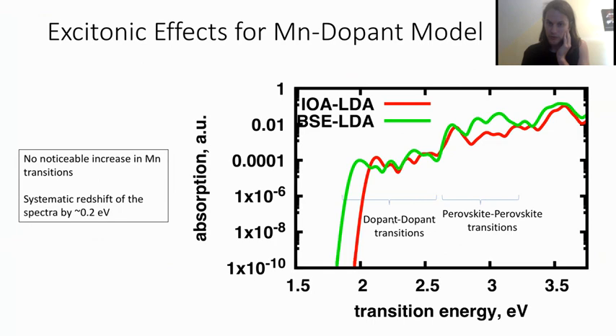So the red line is independent orbital, and the green line is Bethe-Salpeter. The main takeaway is that there's a consistent small redshift of about 0.2 eV. That can be represented as a binding energy of sorts. One thing we were hoping for, or a hypothesis, is that including excitonic effects would boost the oscillator strengths of these DD transitions, since they're very localized. But just from this calculation alone, they're roughly the same order of magnitude. So that's the main takeaway from this slide: a small redshift and not a lot of change in the dopant interactions.